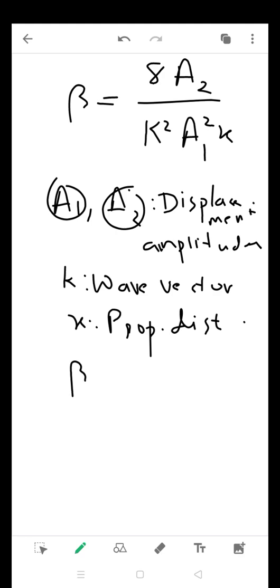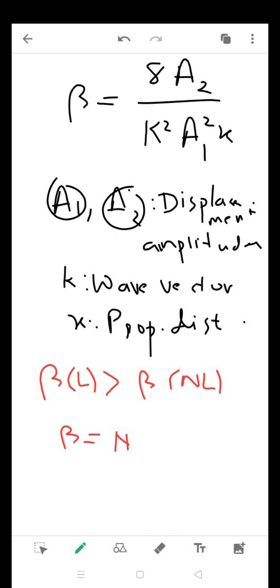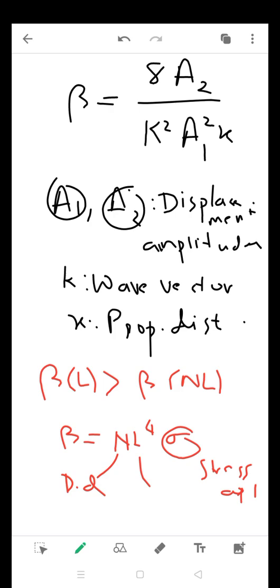Okay. Now this beta, let's put it in a different color. So this beta of the layered sample is found to be greater than beta of the non-layered sample, and beta is again related to the dislocation density and the conduction as N L to the power 4 into sigma. Sigma is the applied residual stress, N is the dislocation density, this is the stress which is applied, and L is the dislocation loop length. So here also you can see that beta is proportional to the dislocation density, and that's how a higher dislocation density will cause a higher value of beta. The higher the value of beta, the better the conduction that takes place.